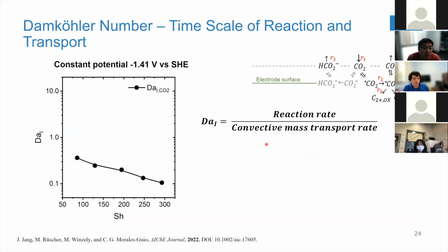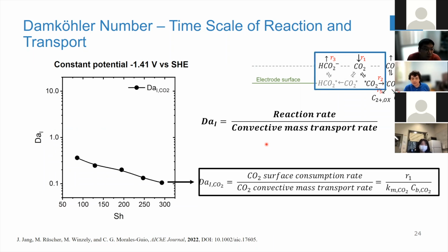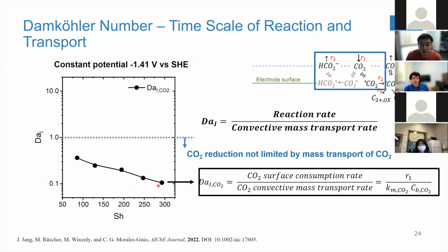So again, I will go back to the Damköhler number. We can look at the Damköhler number for CO2 reduction to understand whether we're limited by transport of CO2 to the surface of the electrode. This is possible simply because all these km CO2 values that we put in these equations are extracted from the hydrodynamics of the cell. Because we know very well the mass transport properties of the cell, we can account for these values numerically. And what we see is that the Damköhler number is lower than 1. So that means we're not really limited by CO2 transport to the surface of the electrode. CO2 reduction is not limited by mass transport.